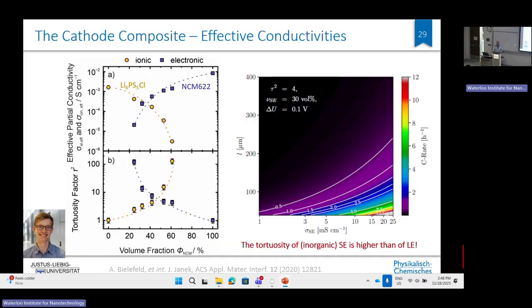And as a chemist, I only learned how to mix liquids, but not how to mix solids properly. That's much more difficult, in fact. So what Philip did, he determined what is really the ionic conductivity and the electronic conductivity. Both are needed in a composite because the electrons from the electrode and the ions from the electrolyte have to come together to store lithium or to get lithium out. So you need two, let's say, good interconnected paths, ionic and electronic, to get a good electrode.